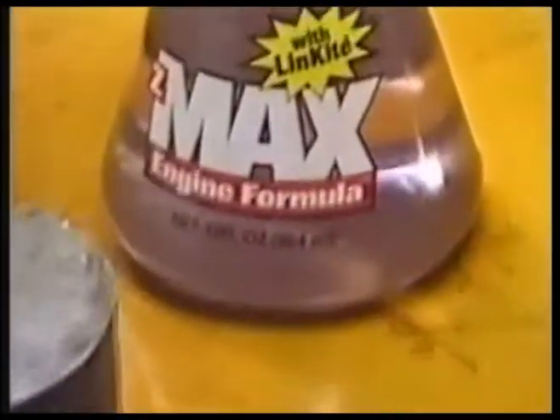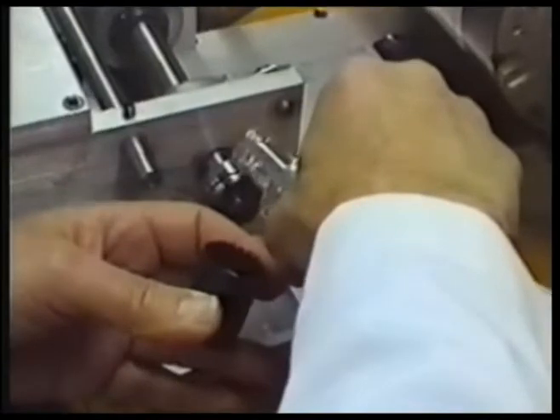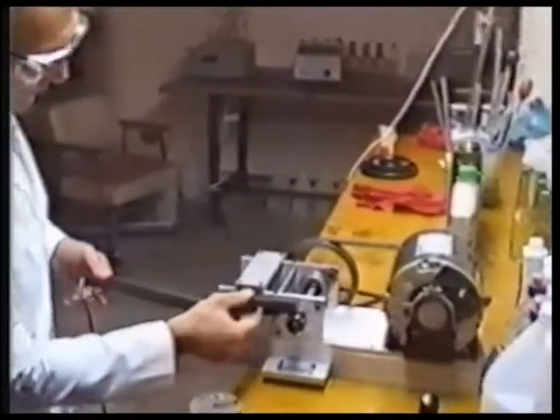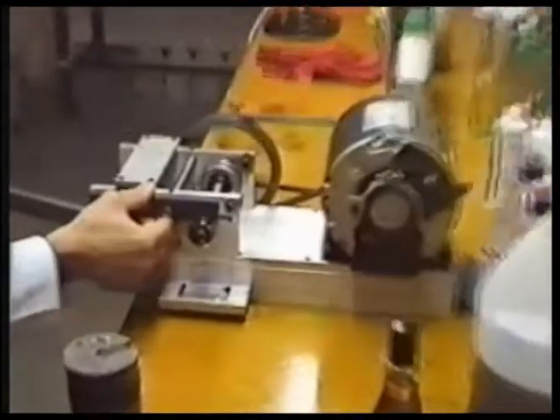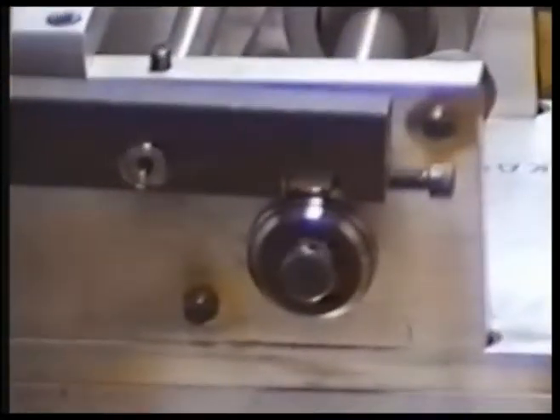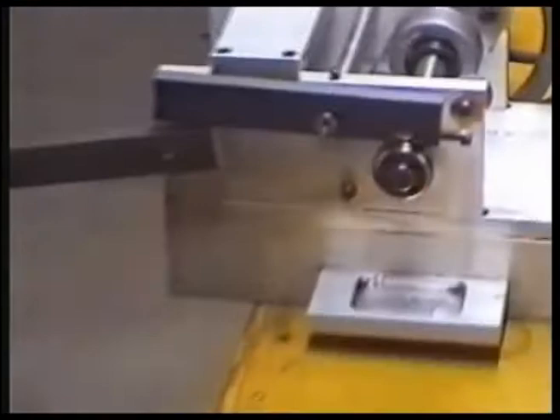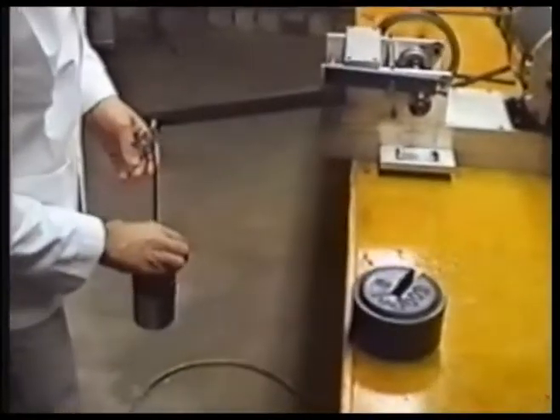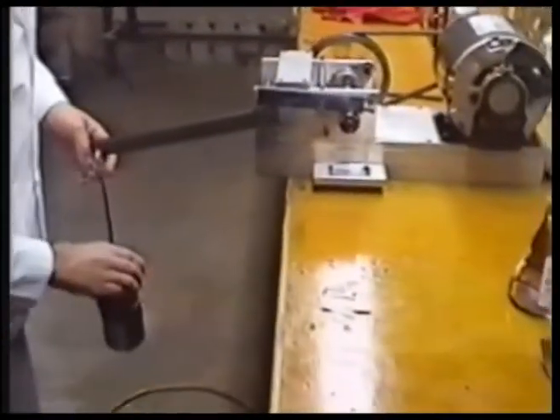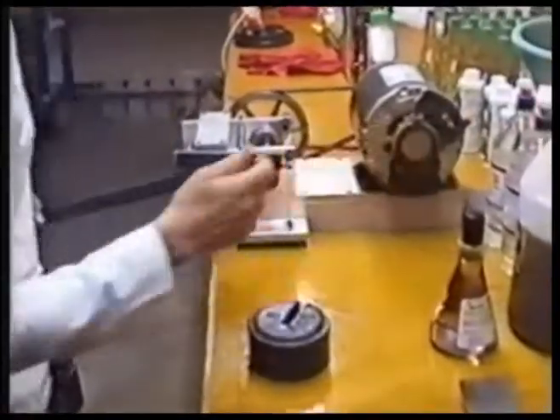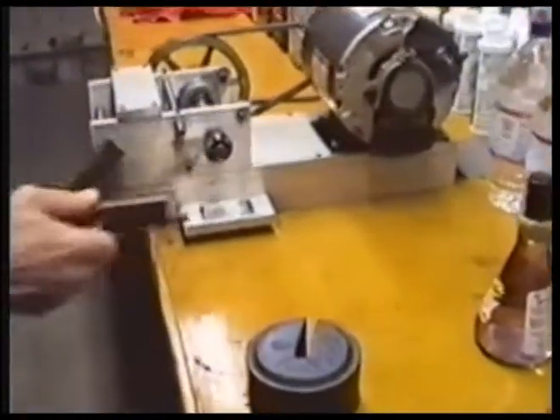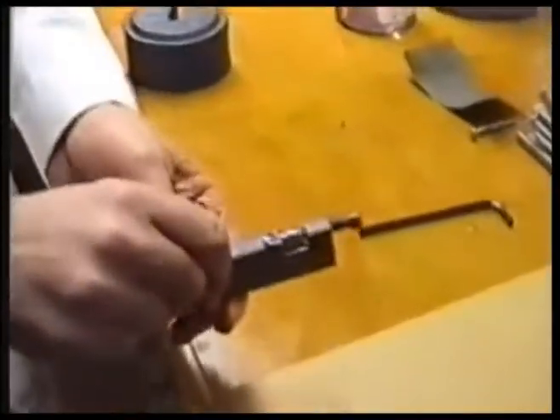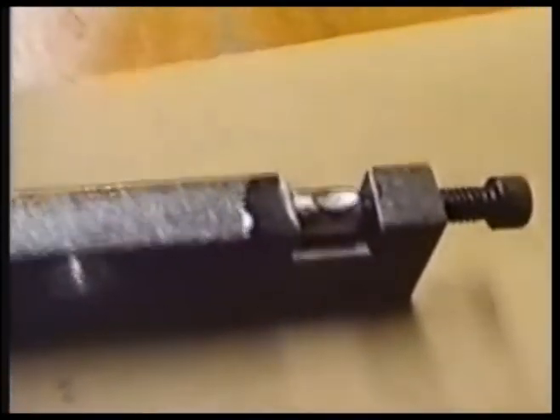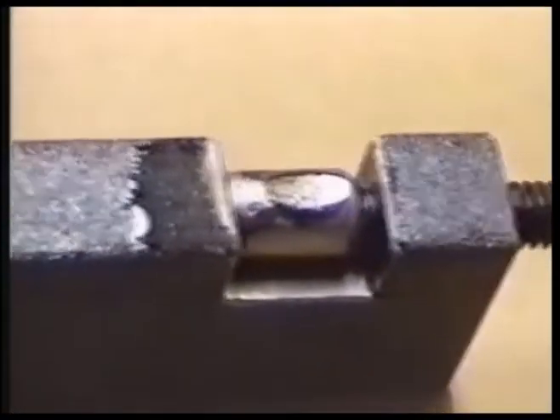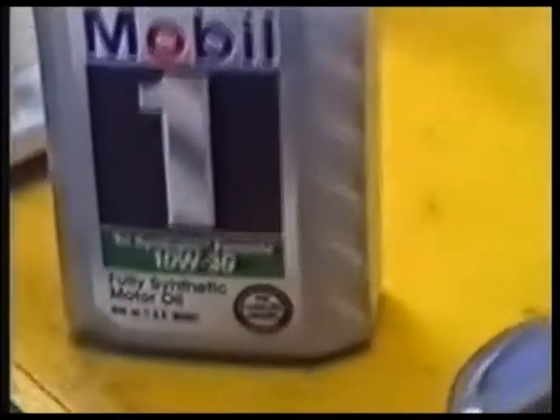The first bearing test is with Z-Max. The product is poured over the test surface and then applied to the bearing surface. And we go. The bearing failed in less than 10 seconds, with less than 17 pounds added to the platform. Visual examination of the bearing after the Z-Max test indicates catastrophic failure of the product to protect the metal from friction. The second bearing test is with Mobil 1.